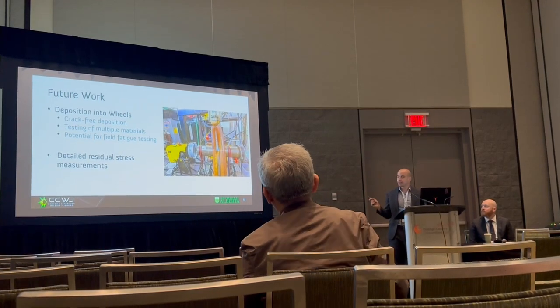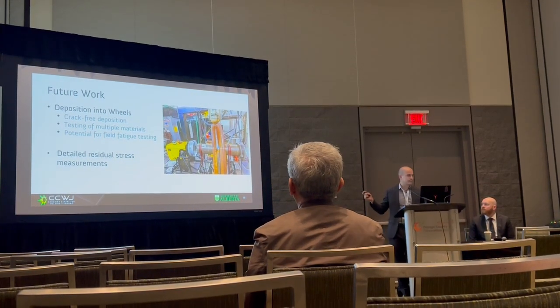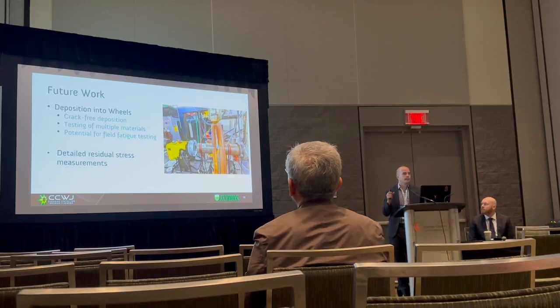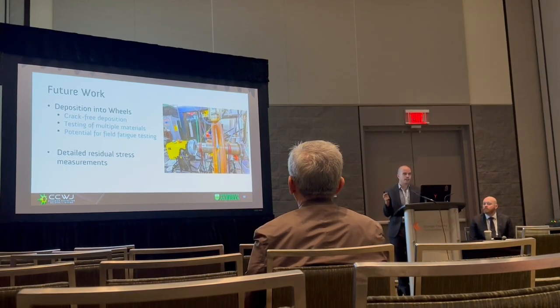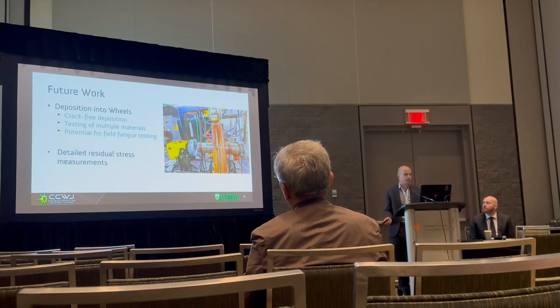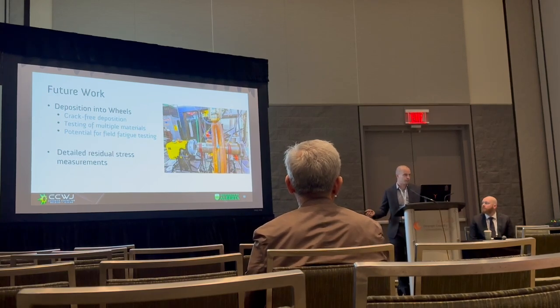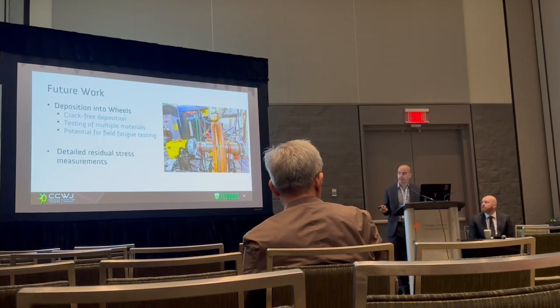And I'm attributing that primarily to the fact that despite the really high cooling rates that occur when you're welding on this much steel, that compressive residual stress I'm retaining in transformation is preventing cracks during overlay and letting us get through to a heat treatment, or sometimes not even needing the heat treatment later.